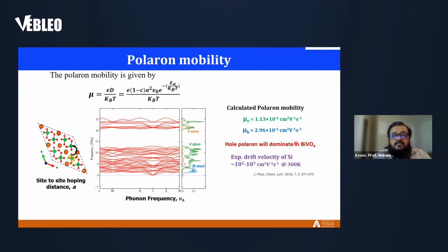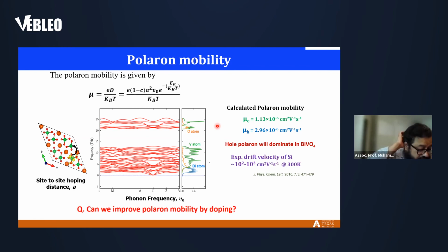Now, if we compare these mobilities with silicon, for example, it clearly shows that the mobility in bismuth vanadate, either of this electron or hole polaron, is 9 orders of magnitude smaller than the mobility in silicon. That shows that polaron formation severely limits the electron or hole transport. Now, a question can be asked: can we improve this polaron-related conduction problem? Can we suppress polaron?